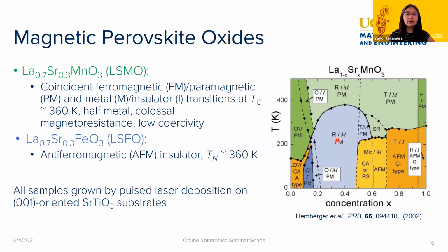So it's been a very heavily studied oxide in the field. And then what we've also looked at is just switching out the B-side element for iron, so one next door on the periodic table. And what we end up with is an antiferromagnetic insulator. And at least at this 30% strontium doping, it has a Néel temperature which is somewhat similar to the Curie temperature of the manganite.